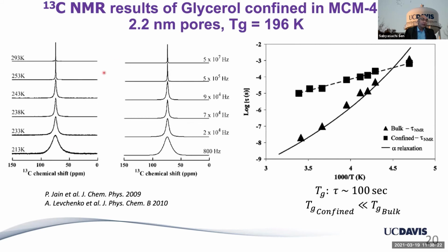So here are a bunch of experimental carbon NMR spectra of that carbon site in glycerol. I'm just showing you the confined glycerol. We also collected data on bulk glycerol, obviously, as a starting point. And then what you can do is you can simulate these line shapes at different temperatures. And again, you have to take my word for it that this is theoretically very well understood how to do these simulations, very standard in NMR literature at least. And by simulating, you can get the dynamical rotational time scale of the glycerol molecules, how fast they're rotating.